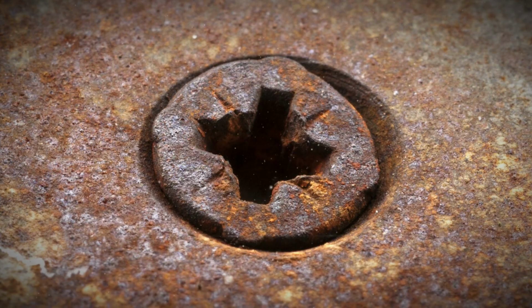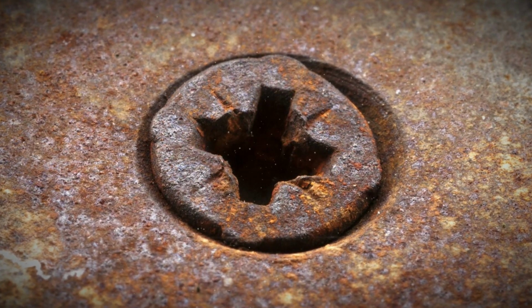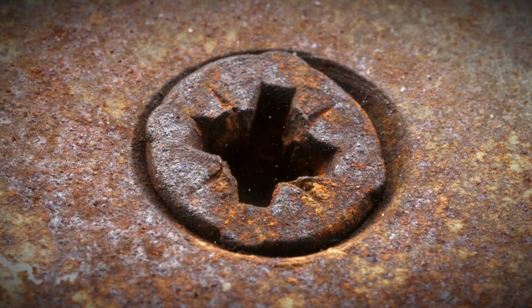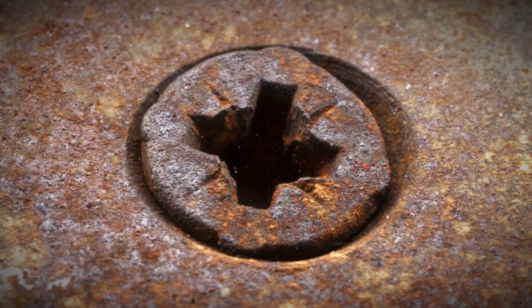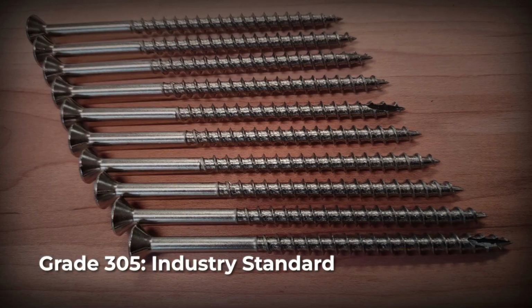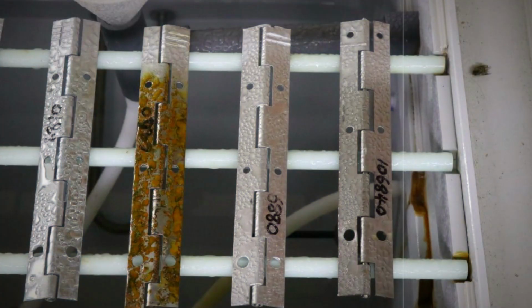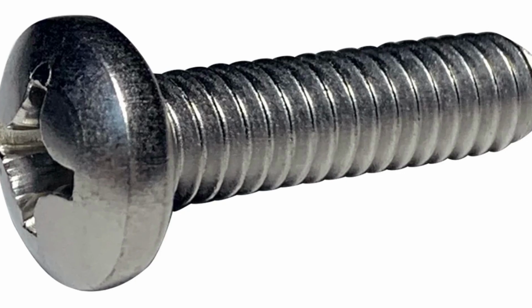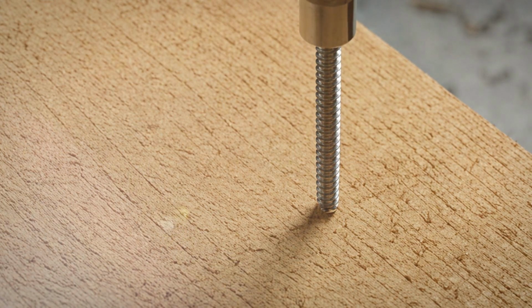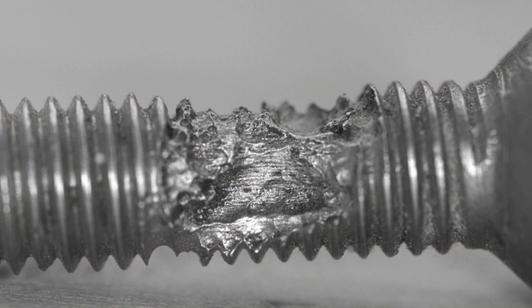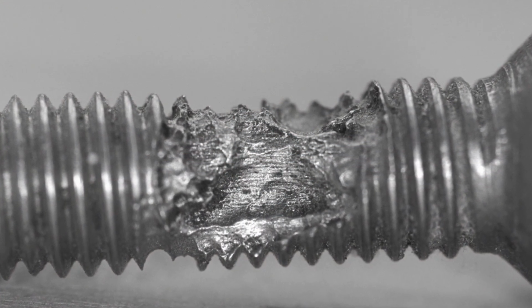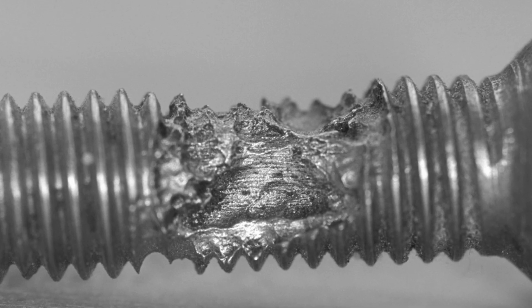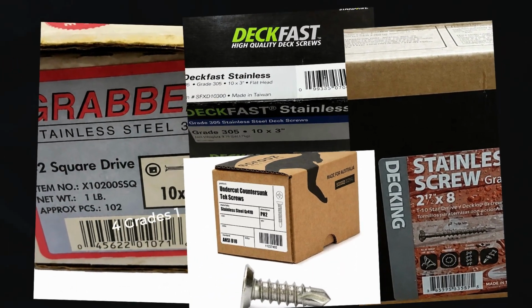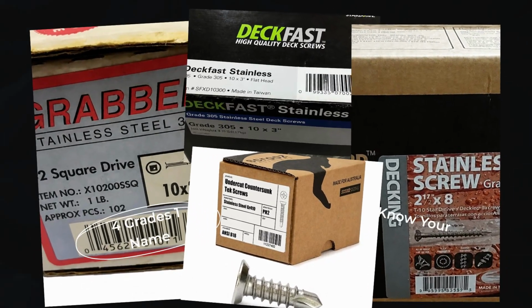Grade 302 is considered low-quality stainless, offering minimum corrosion resistance and not recommended where anti-corrosion actually matters. Grade 305 is the industry standard for general outdoor use. Grade 316 is the marine choice, with molybdenum added to resist pitting and salt damage. Then there's 410. It's harder and stronger, which sounds like an upgrade, but it's notably less corrosion resistant, and it does not belong in wet or salty conditions. All 4 can legally be sold to you as stainless steel deck screws.